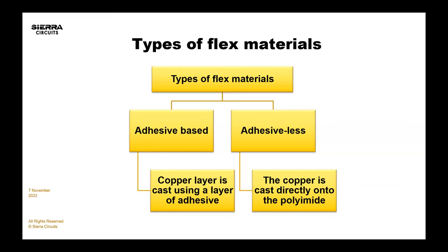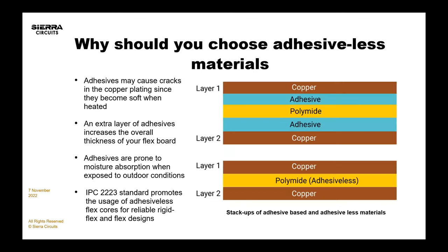Adhesive can cause all sorts of reliability issues. Be very aware of whether you're using an adhesive-based or adhesive-less material set. For example, when you're trying to clean the inside of a via using plasma, that adhesive may react differently than the other materials in your stack-up, especially in a rigid flex stack-up. You have to be careful of reliability issues like wicking, proper etch-back, and dendrite growth.